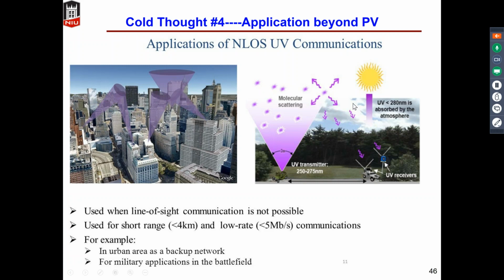In the lower level of the air, there is no UV light below 280 nanometers, because most of these high energy UV photons have already been absorbed or scattered by the upper level atmosphere. So when you generate such UV photons with a transmitter, it won't be interfered with by other UV photons at the same frequency from the solar light. But you need a sensitive receiver to receive this scattered UV light, and the propagation range is typically just a few thousand meters. So this can secure the information within just the desired range.